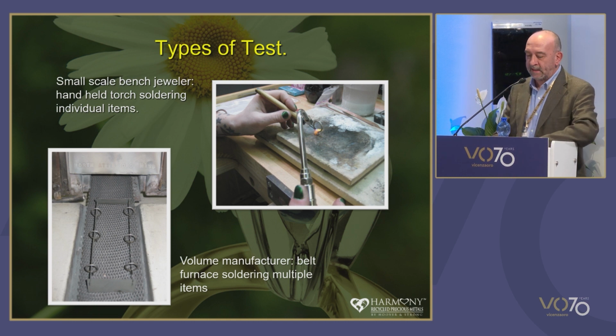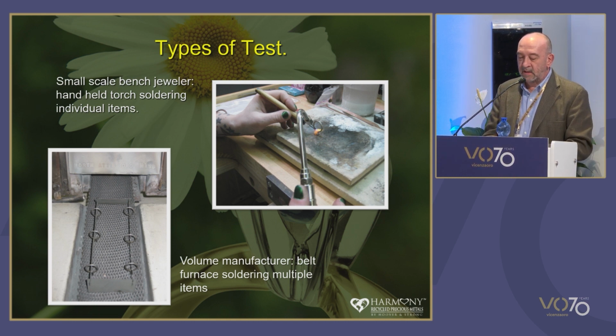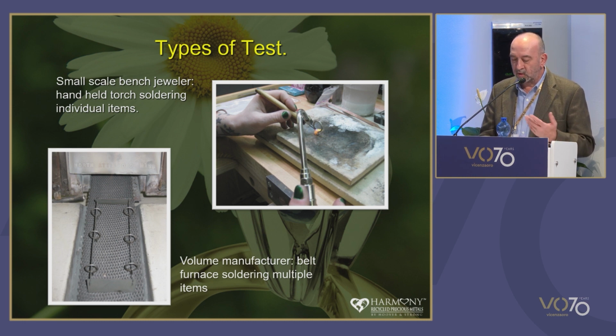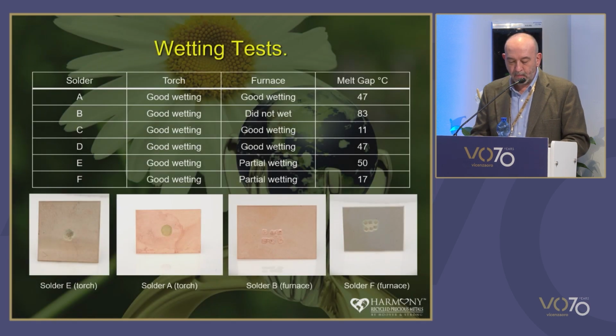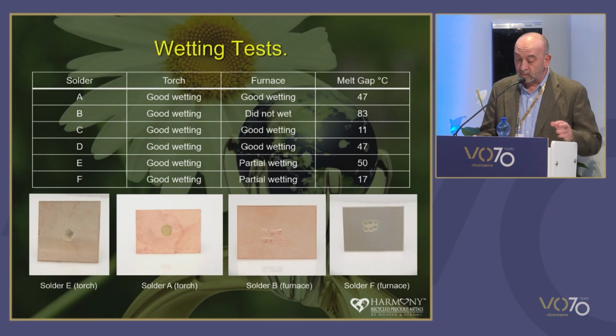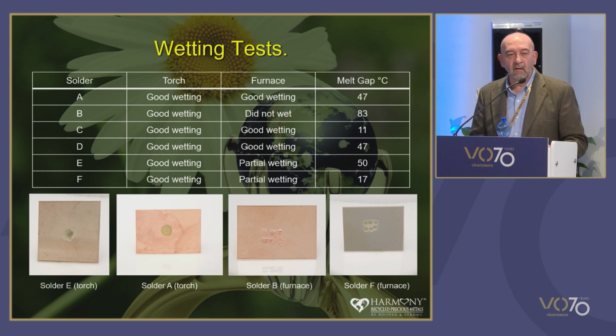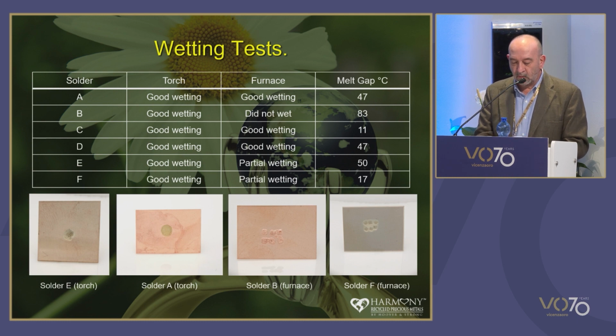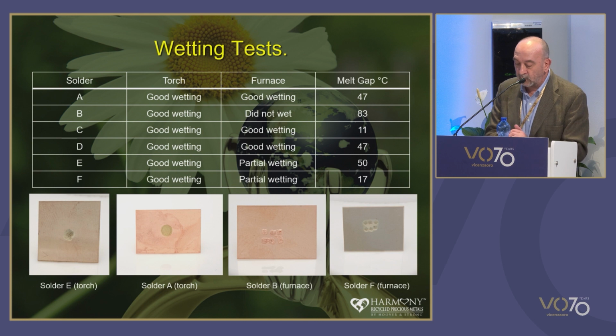So the first test we performed was a wetting test. We took 6 pieces of each solder and placed them simply onto a piece of carat gold sheet, and then they were melted using the 2 methods outlined above. This would give us an indication of how well the solders wet the parent metal under each condition. As we can see from the results table, in the second top column entitled torch, the torch soldering tests all showed full liquation, the solders wetted okay, there was no balling, and there was no evidence of residual solder left. There did not appear to be any noticeable difference between cadmium and cadmium-free solders.